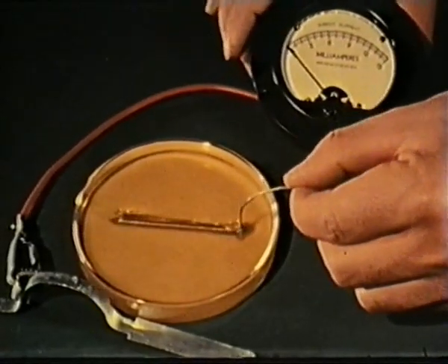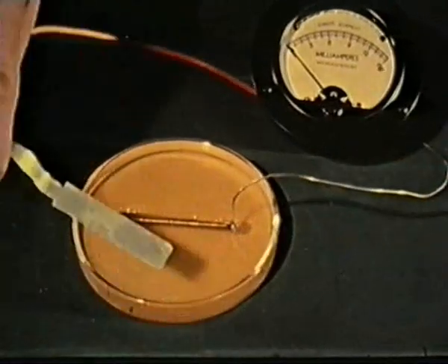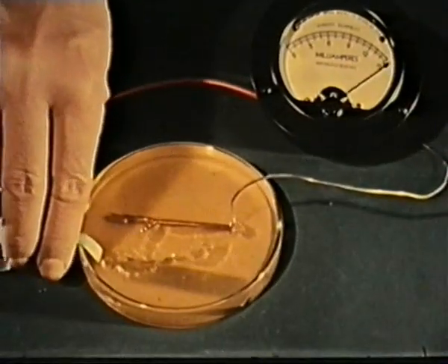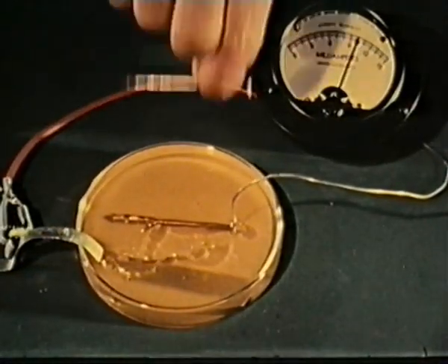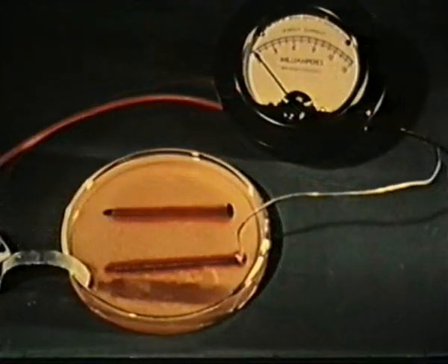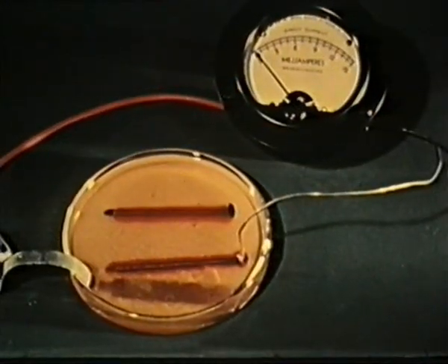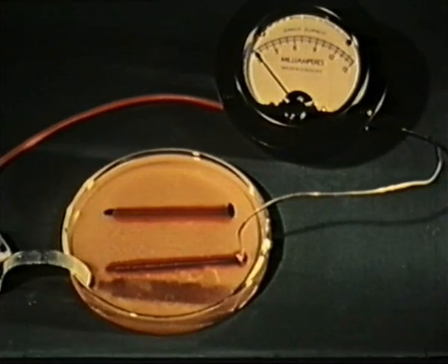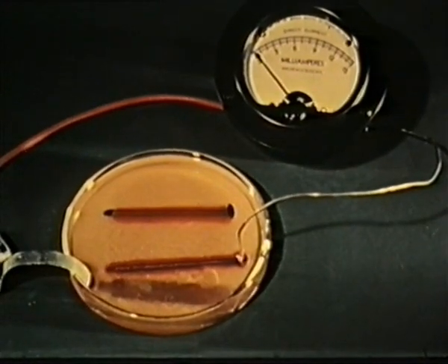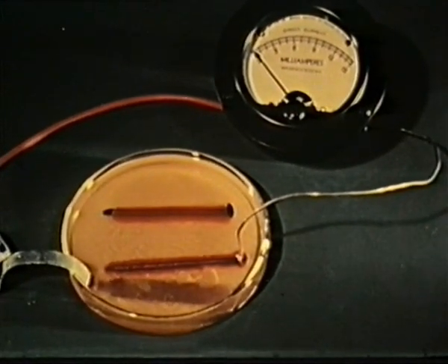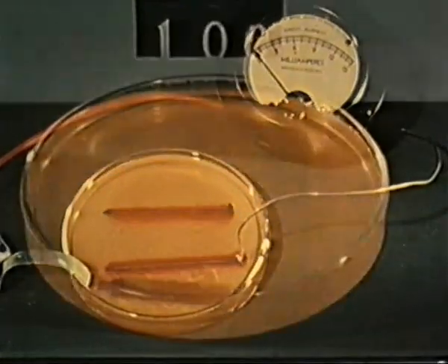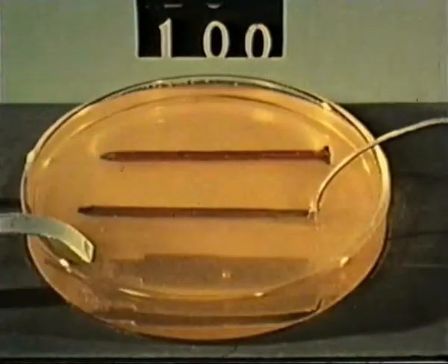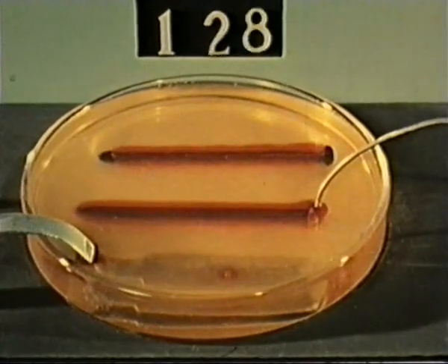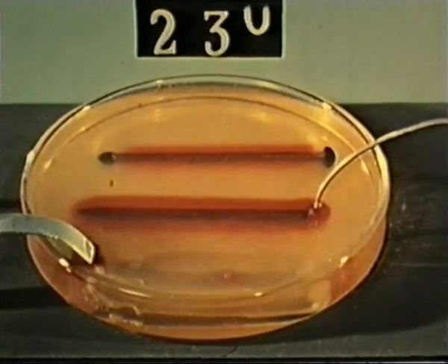In the first case, we used zinc joined electrically to an iron nail as the source of the protective current, which makes the iron act as a cathode all over, as evidenced by the development of the red color, showing the presence of the cathodically formed alkali. Note the absence of any blue color on the specimen receiving current from the zinc. Final development of this color requires several hours, but we can follow it by stop-motion photography.